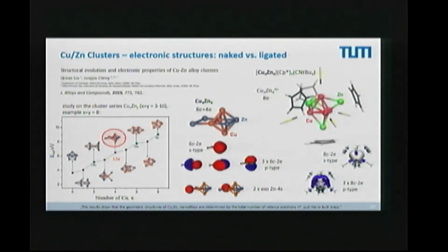So this di-zinc unit does not contribute to the superatom closed shell situation of the octahedral packing. Now, why is our system integrating all metals in high symmetry? This is just because we reduce the total valence electron count by 4, because the electron affinity of the Cp* ligand is very high. So it takes an electron from the metals to Cp*-. So we have not 12 electrons, we just have 8 electrons. And 8 electrons is 1s2, 1p6, which makes 8 from the